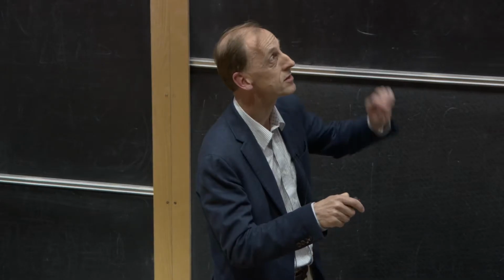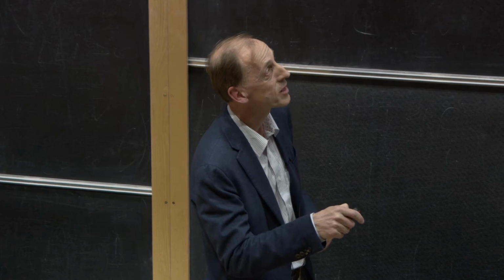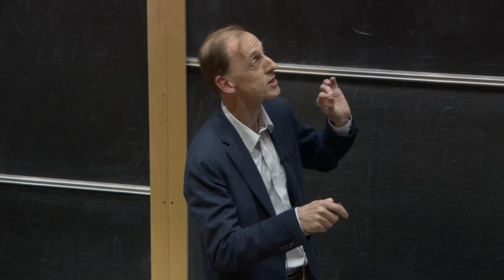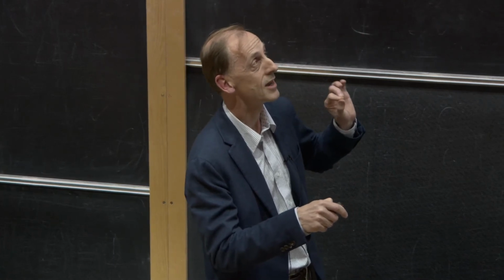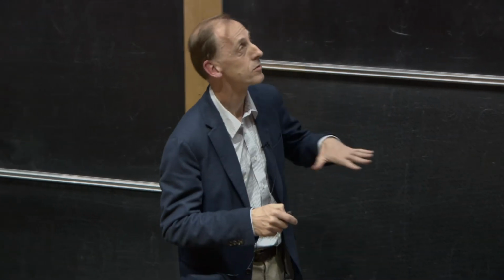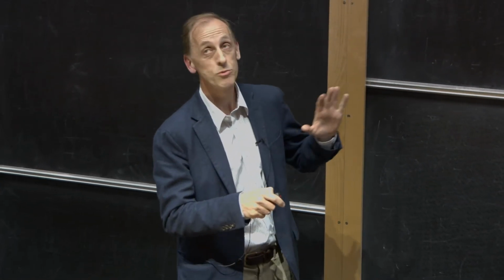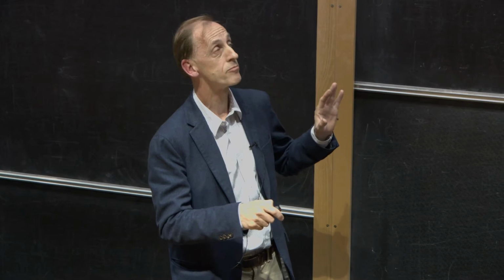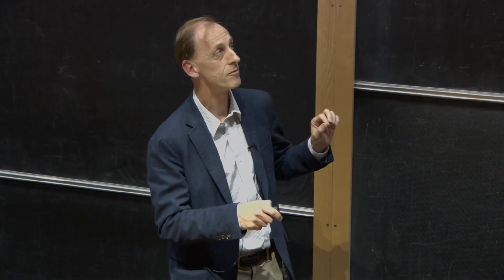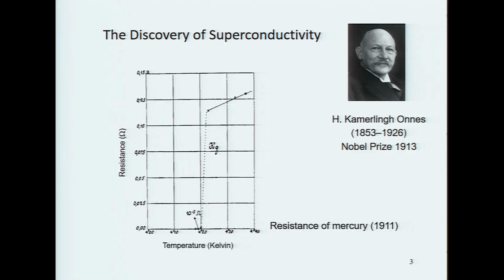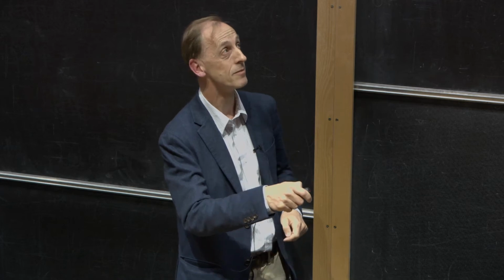And you can see here he's written by hand 10 to the minus 5 ohms. That was the lowest he could measure the resistance of mercury with his apparatus. So it was like an upper limit. And actually, when he first saw this, he thought there must be some problem with the apparatus, because actually 4.2, which is this axis temperature here, this is exactly the temperature at which helium liquefies. So he assumed that this was just a spurious effect due to the liquefying of helium.